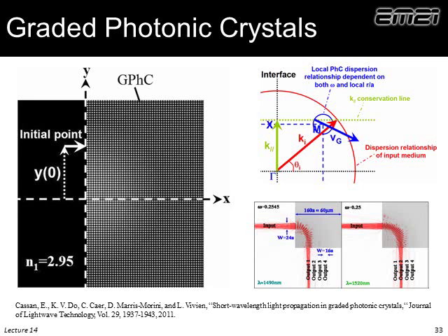In the end, we're doing the same thing. We're grading refractive index. However, we're using a photonic crystal effect in one case where you're riding the dispersion curve near a band edge. In the other, the holes are spaced so sub-wavelength that it's really just an average effect producing the graded index.